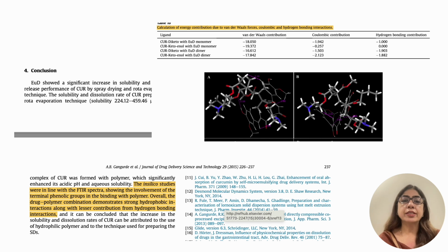Now, if we look at the results of the molecular dynamics simulations, they revealed that the van der Waals interactions contributed more to the total energy of the complex than hydrogen bonds. This is consistent with expectations for solid dispersions. In solid dispersions, it is preferable for the drug-polymer interaction to be strong enough to enhance the solubility of the complex, yet weak enough to dissociate easily in physiological conditions.